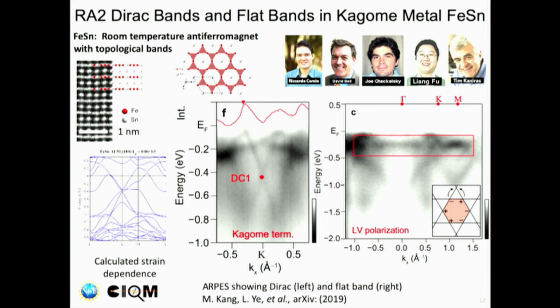And since then, there's a technique called ARPES, which is angle-resolved photoelectron spectroscopy, that allows you to look at the energy bands, that is energy versus momentum, near the surface of a material by blasting it with photons, and then looking at what comes off. And by doing that with Ricardo Comin, who's a new junior faculty at MIT, they saw both the crossed bands and the Dirac point shown here, and they also saw the flat energy band that we've been talking about, shown here in the real material. And so that proves that it actually works.